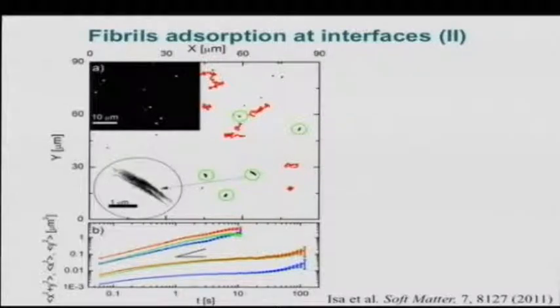This is the mean square displacement in 2D versus time. The slope is 1. They are fully isotropic. But the particles on the interface have a 1D hopping motion, okay, and they are strongly subdiffusive. So this is in line with the fact that we do know already that the interfaces are viscoelastic. But the new piece of information is that there is a 1D hopping motion.